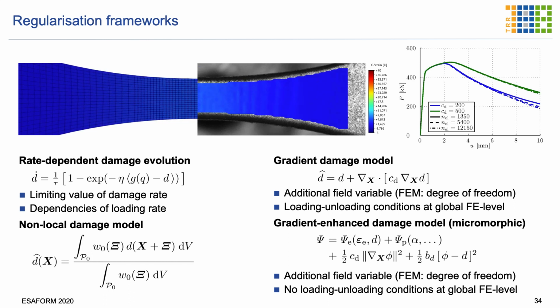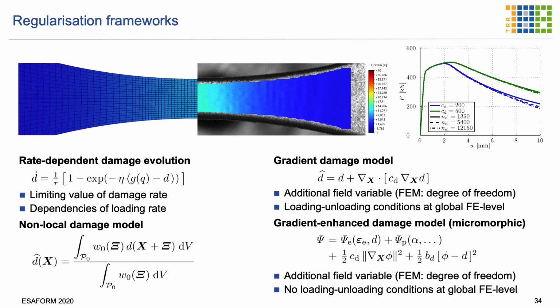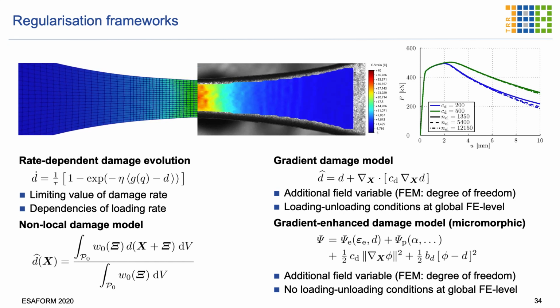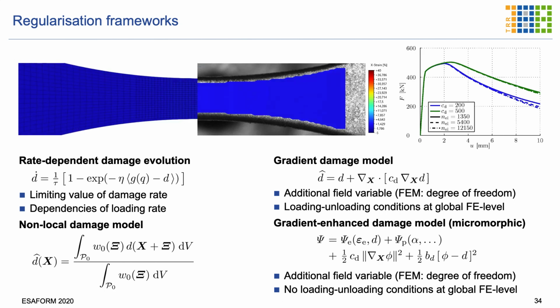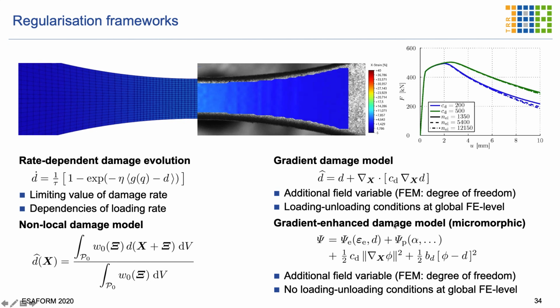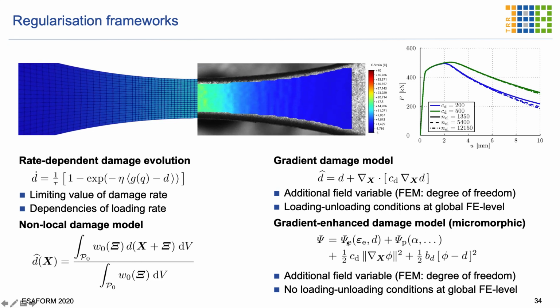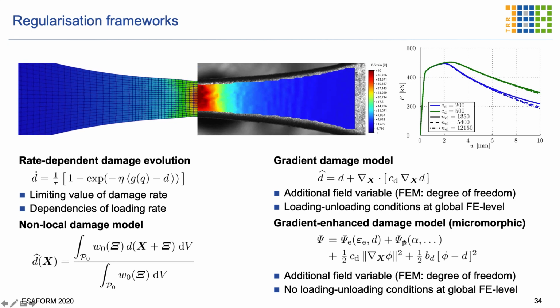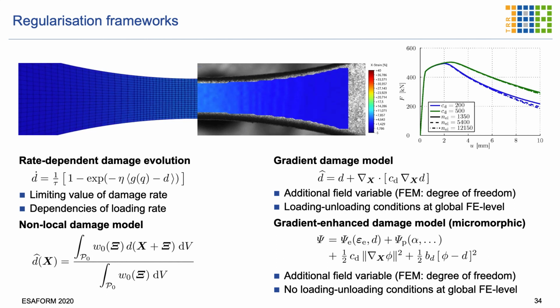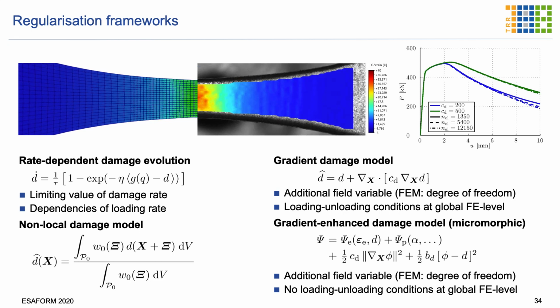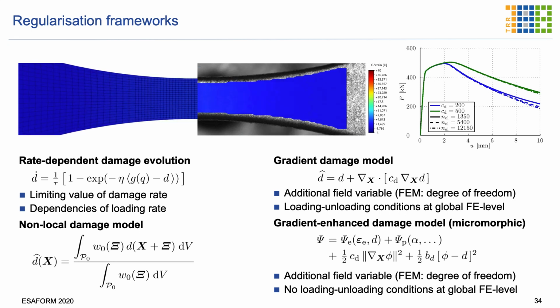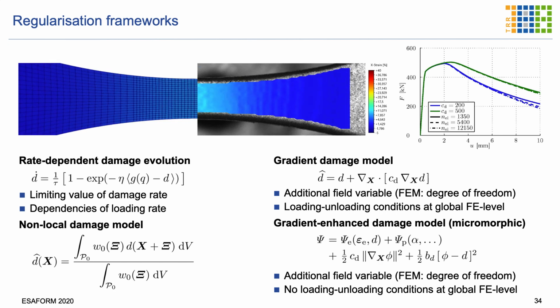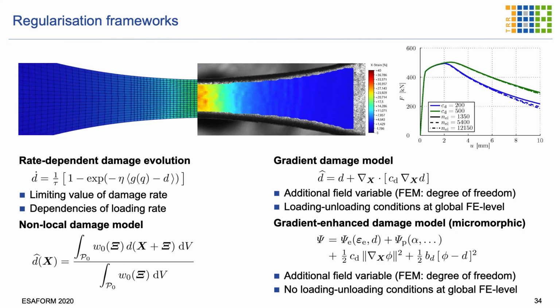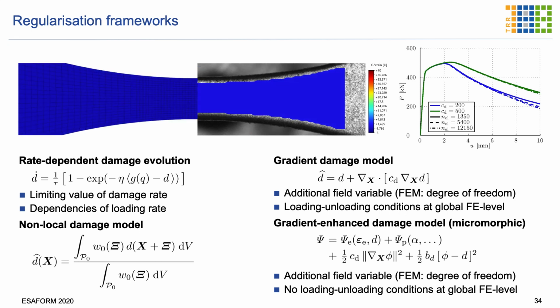With those, we went also to develop our macroscopic and multi-scale models. I'll give you an example for the macroscopic models. This is a gradient enhanced damage model, which has, beside the elastic and the plastic contributions, also a contribution for the gradient damage model. And our model has a very special property that all the parameters, the plasticity and the damage, are decoupled, so you can have a multi-surface analysis and reflect in a very flexible way the properties of that model.